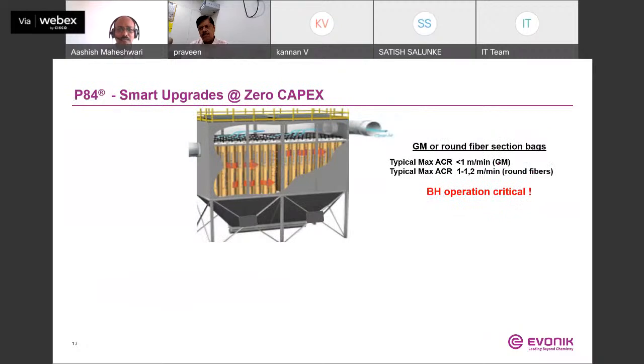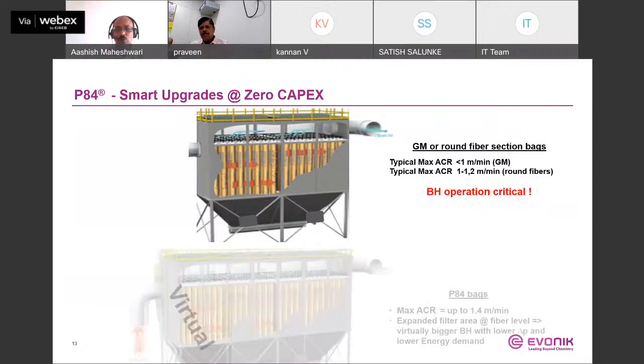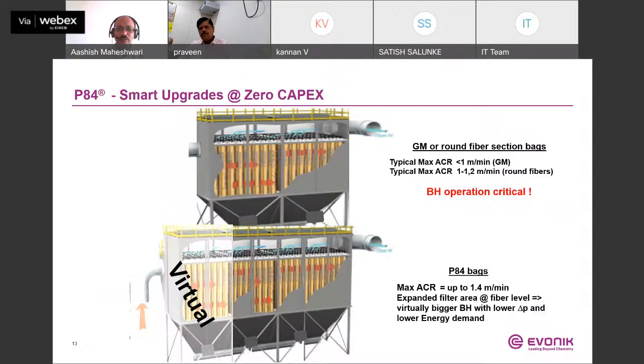At the same time, normally the glass membrane or round fiber can operate at a maximum air-to-cloth ratio of around 1.2. Ultimately, that is a limitation when you are increasing the production and the gas flow rate. Whereas P84 bags can handle a higher A/C ratio, up to 1.4 meters per minute. So you have a virtual filter bag filter, which can play a crucial role in lowering the DP and energy demand.